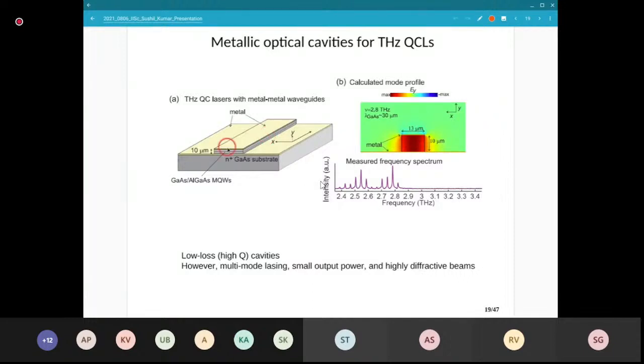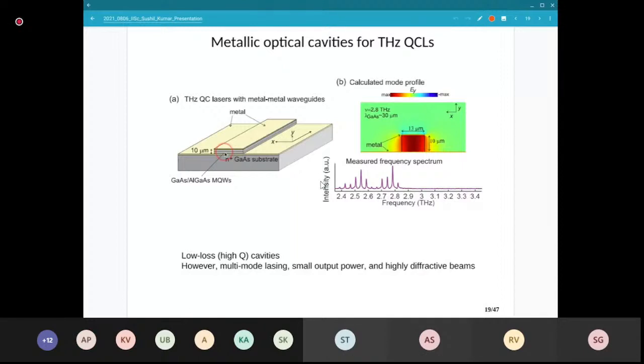It has metal on the top, a metal plane on the bottom, and this QCL superlattice structure is sandwiched between these two metal layers. This sandwich has about 1,500 layers which have been grown by MBE, about 10 micrometers thick. The wavelength inside, propagating back and forth, is, let's say, inside gallium arsenide 30 microns. So you can see there is no cutoff. You can keep it thinner, it still works, and it can confine terahertz light.